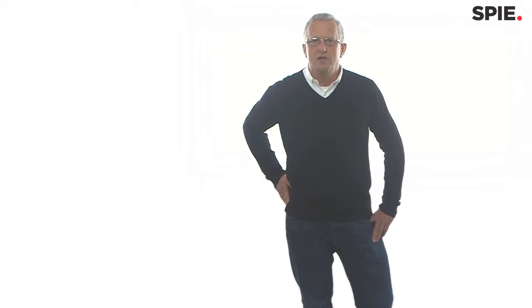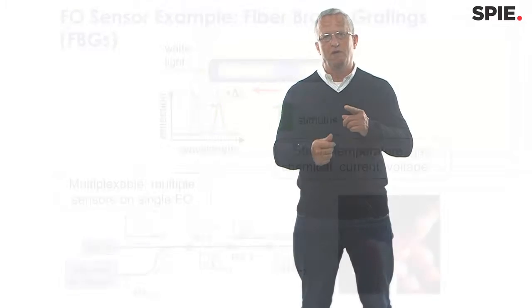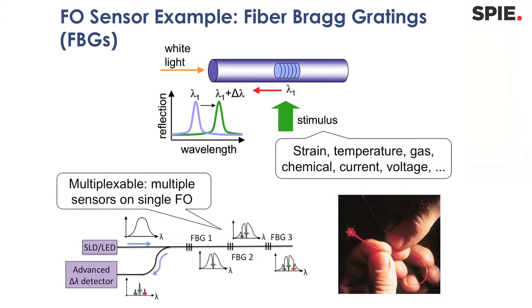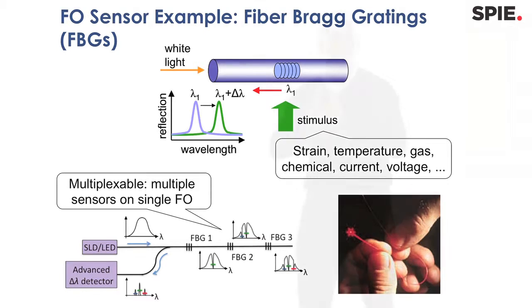Currently fiber optic sensors, let me come to one prominent example, the fiber Bragg grating sensors. You are using UV interference pattern, for example, to inscribe the Bragg grating. The Bragg grating is nothing else than a small mirror, and if you heat the location or stretch the location, then the periodicity of the refractive index modulation is changing, and therefore the reflective peak is slightly moving, and that's what you measure.